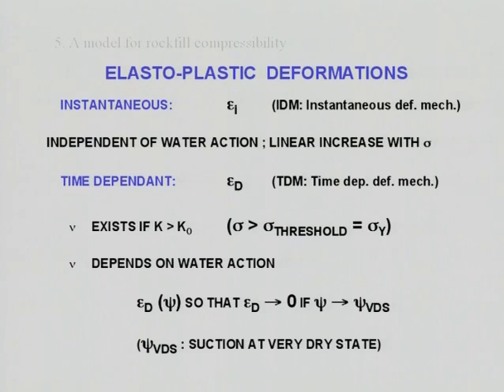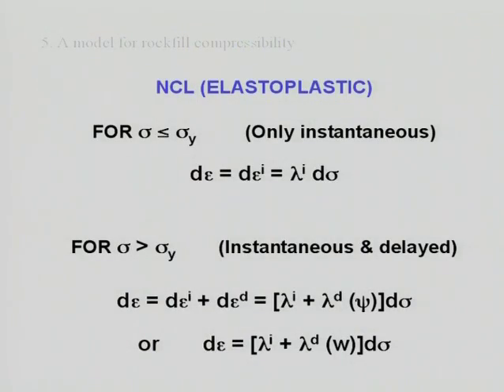And then time dependent. The time-dependent part exists whenever our stress is larger than a threshold. This comes from the underlying theory. This comes also from the experiments. But we recognize that they depend on water action, so we should write them in this way. This should be a function of the prevailing suction, or relative humidity, or vapor pressure, any measure of the energy of the water. It should be 0 if our suction goes to a very high value, so we are in a very dry state, where presumably cracks don't propagate. And then it is relatively simple to build a model.